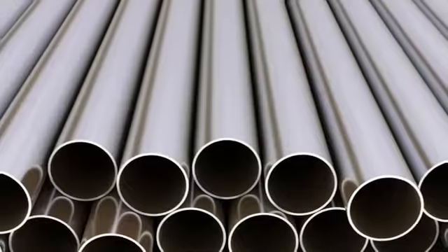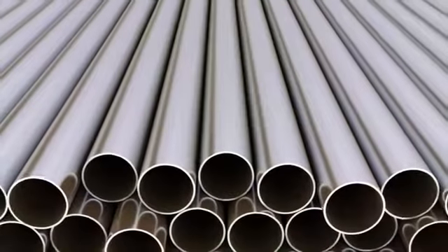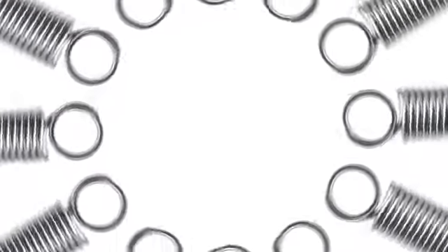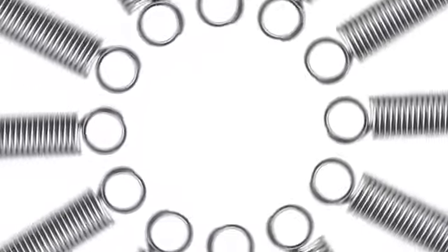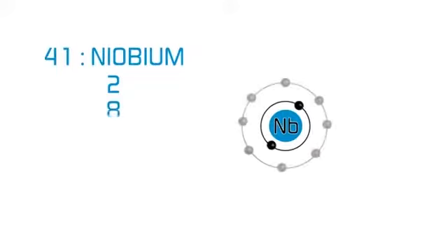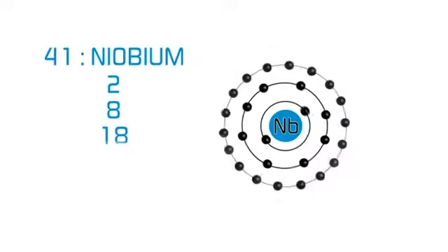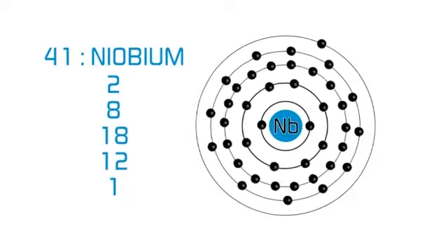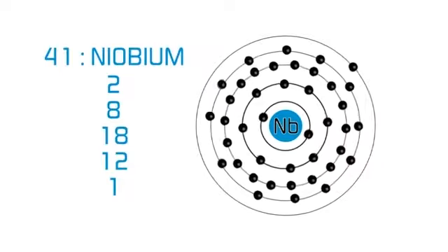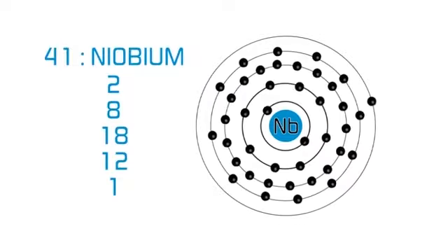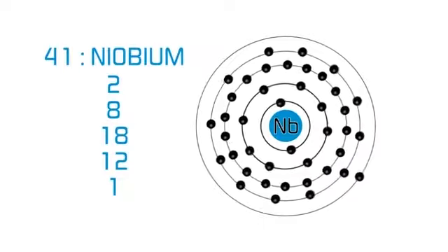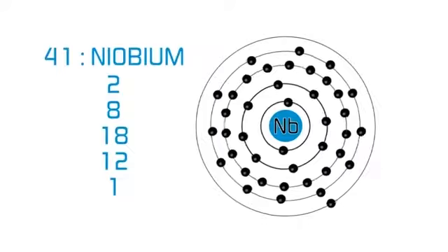Austenitic stainless steels have high ductility and a lower yield strength than some of the other variants, and niobium plays a number of important roles depending on the specific application. Niobium has a large atomic radius and is capable of straining the austenitic lattice to such an extent that, in combination with its grain refining effect, due to the formation of fine precipitates of niobium carbide or niobium carbonitride, it significantly increases the yield strength of the austenitic grades.